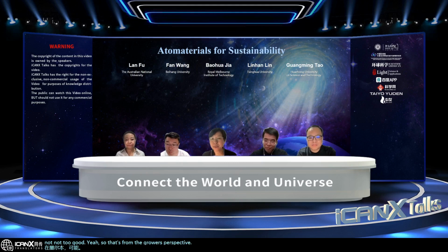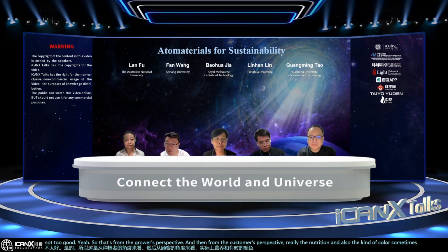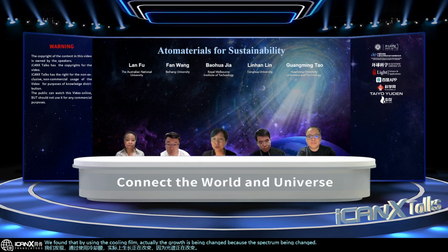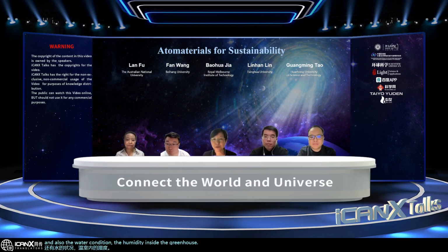And then from the customer's perspective, it's really the nutrition, and sometimes the color, and also the size of the fruit. We found that by using the cooling film, the growth actually changes because the spectrum changes, and also the water condition and the humidity inside the greenhouse. In that case, we found that for lots of plants, the nutrition actually increases, and the size of the fruit also increases. So that's all good news.